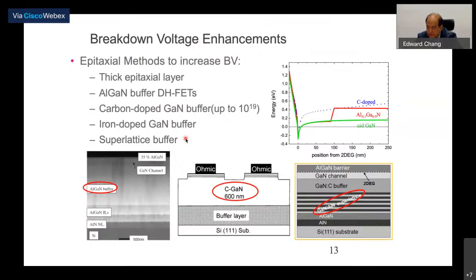And then you can use different dopants, like carbon, like iron, and then you can also use a superlattice as a buffer, okay, to reduce the leakage current. Those are the common methods used to increase the breakdown voltage of gallium nitride devices.